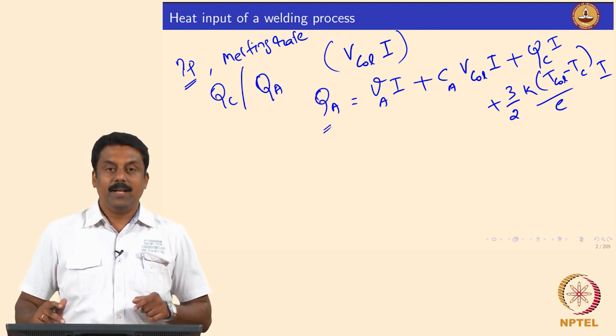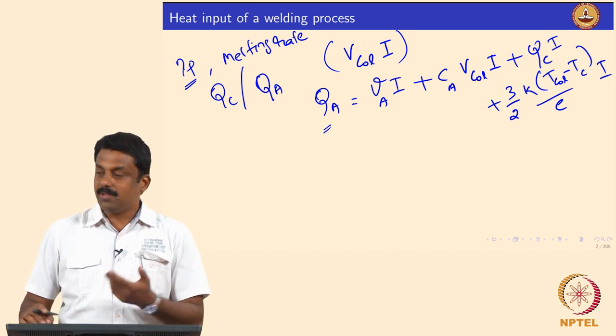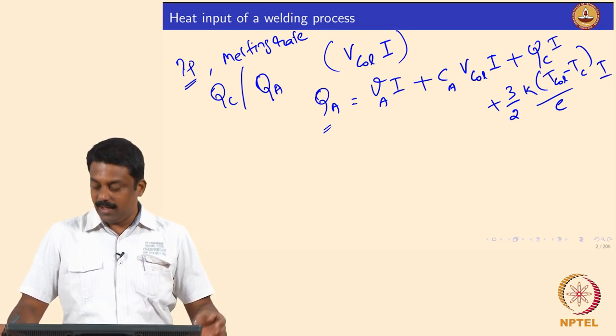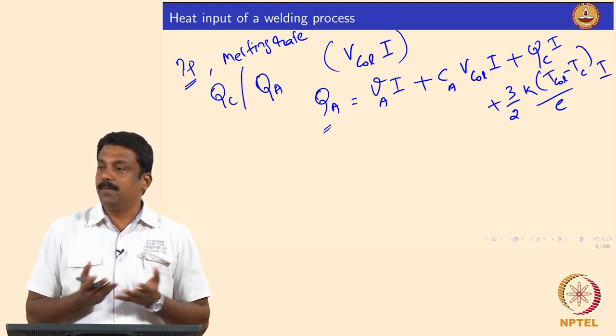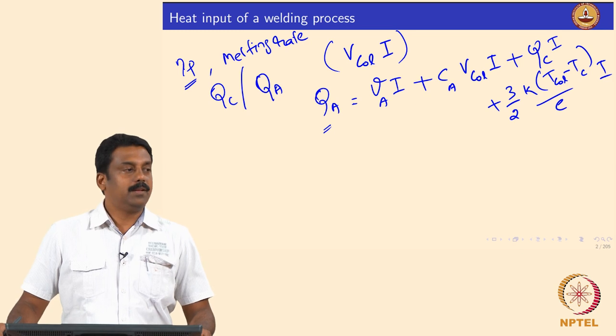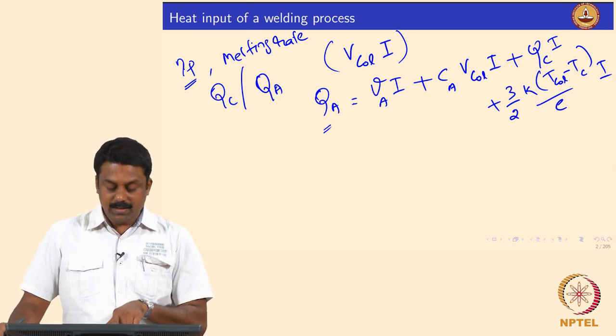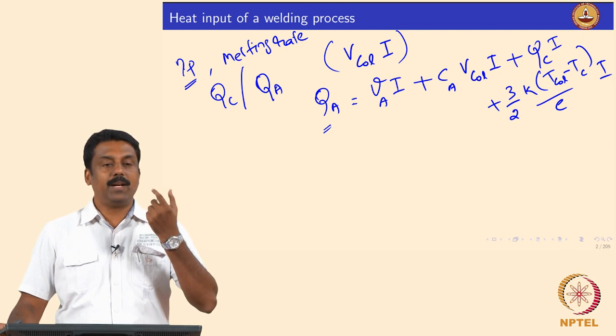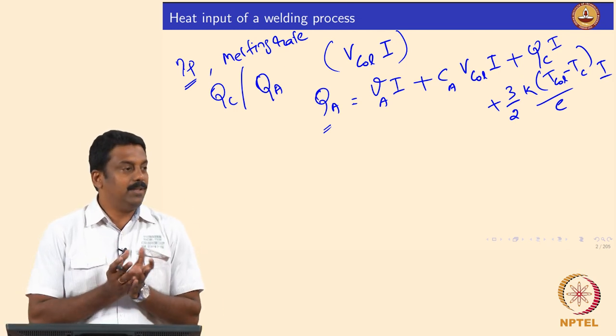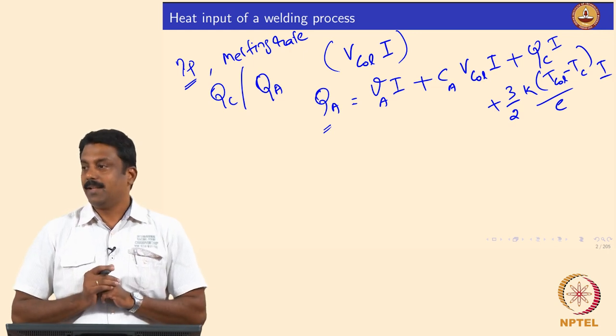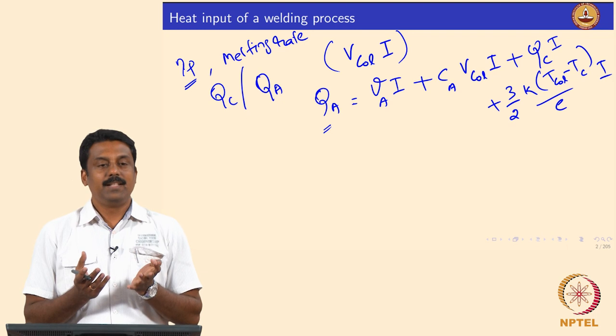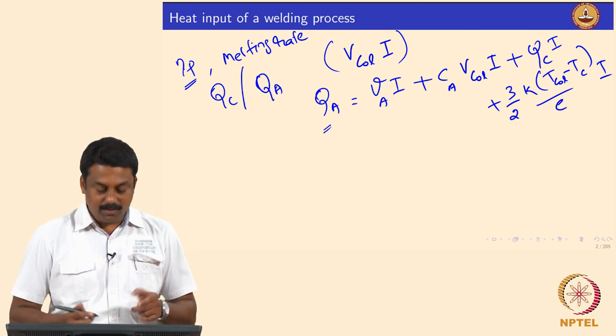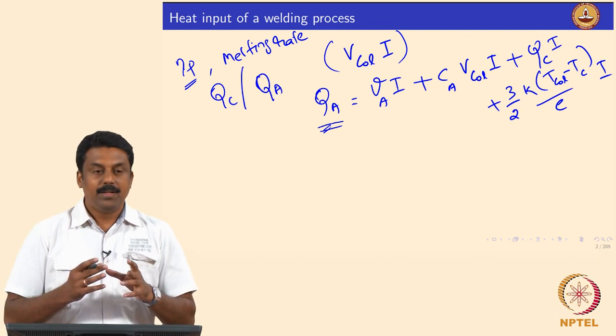All terms in the anode are positive, which is why the temperature is always higher in the anode. In the cathode we have minus terms — the work function is spent and electrons absorb heat as they are heated to arc column temperature. This gives us the heat available in the anode and cathode. If the consumable electrode is made the anode, this heat is available for the droplet to melt, plus additional heat from resistance heating.